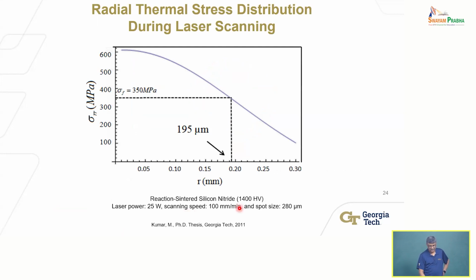It has a Vickers hardness of 1400, and it's being irradiated with a laser at 25 watts at a certain scanning speed and a spot size of 280 microns. Under those conditions, this is looking at the radial thermal stress distribution, right? And the fracture strength of this ceramic is 350 MPa. So in this, I put 350 MPa, right?